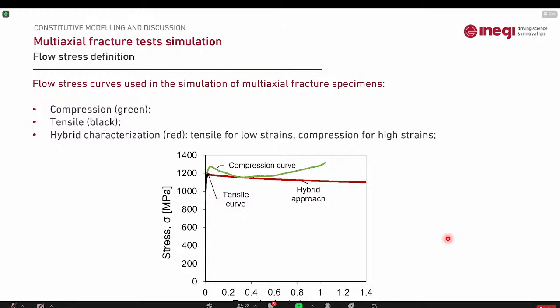So you have some issues with elongation at break, right? Exactly. When it's a compression test, you can obtain very large strains. When it's a tensile test, this is not a percentage; it's actually the strain. So yeah, sure, but it's still 100% here. Yeah, but still, it's about 4% or something like that. Yes, and I also noticed that the conventional material is much more ductile than the additively manufactured. Yeah, but that's always the critical thing.